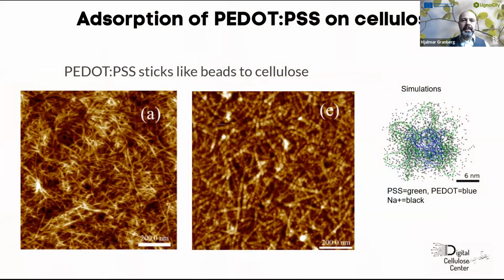We've also looked at the interaction between PEDOT:PSS, which is a conducting polymer, the PEDOT, and then cellulose. These stick together. Here to the left, you can see the nanocellulose as a network. And when you add the PEDOT:PSS, these end up as beads like this. This means that you can end up with a network, a conducting line, which is good for a high conductivity.